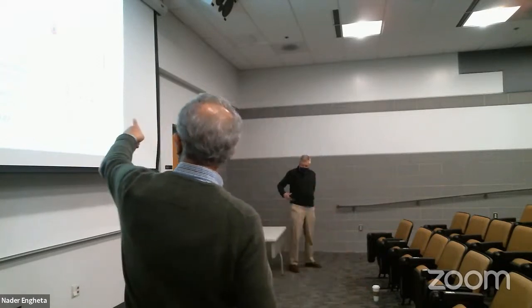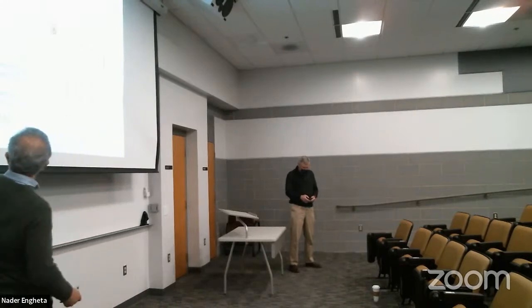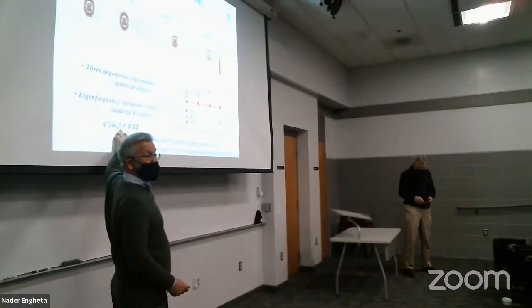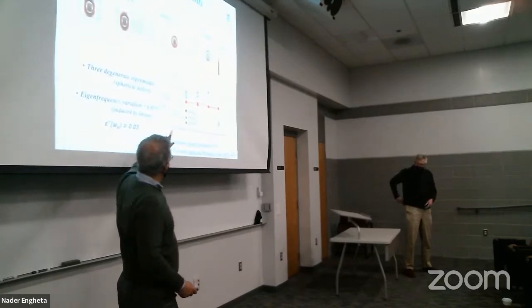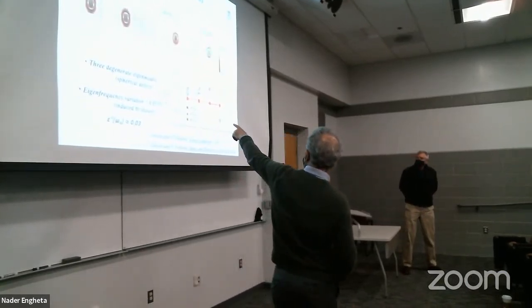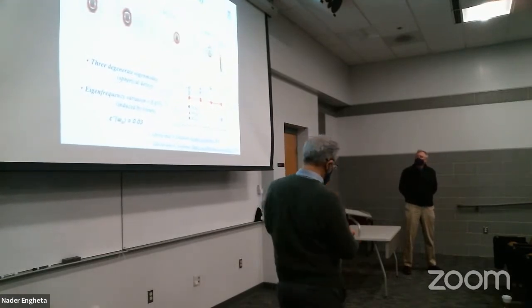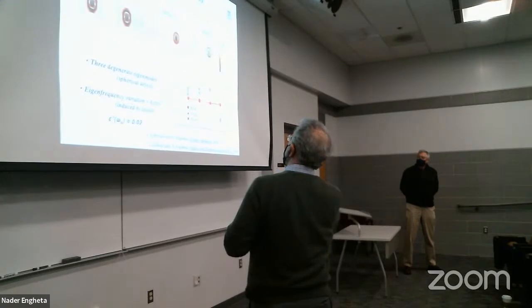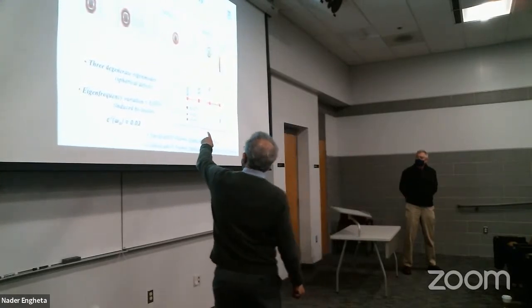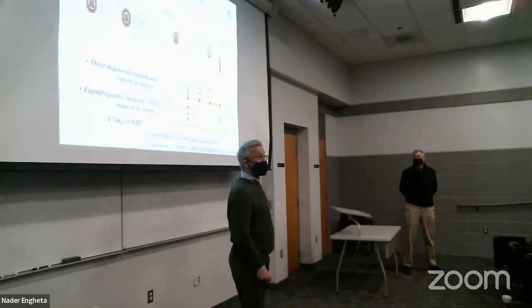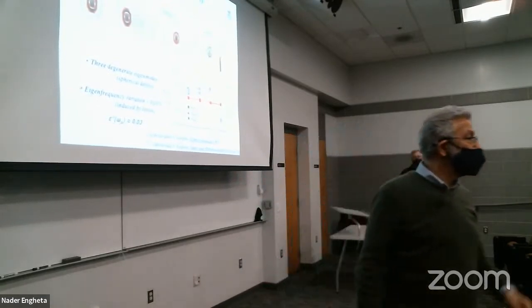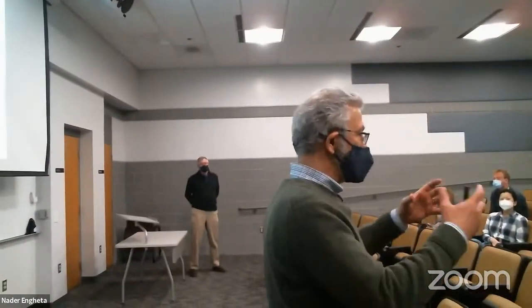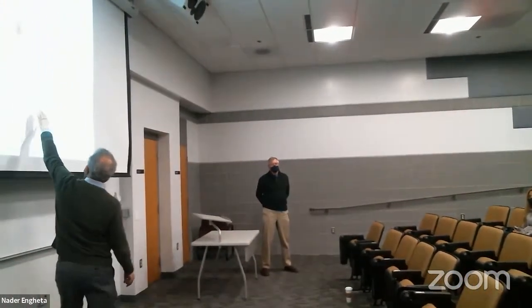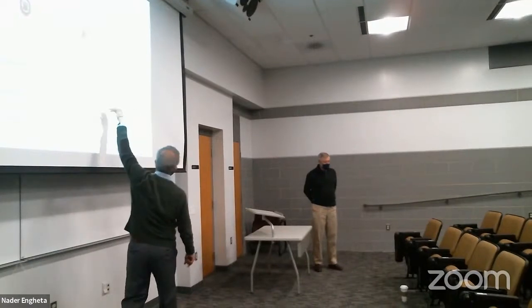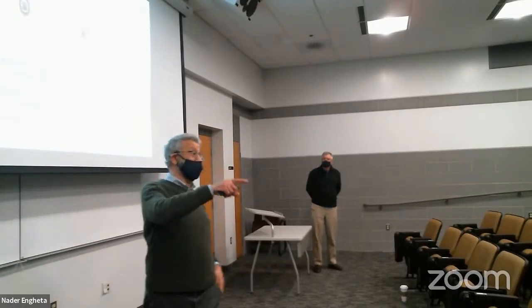In this one, we actually use the realistic material of silicon carbide with an epsilon double prime of 0.03. With this structure, you notice that the resonant frequency is almost unchanged, by the way, for these four cavities that you see over here. But look at the blue dots, and you see the range of the Q that you have there. So yes, obviously the Q deteriorates. And this is actually interesting because even though the resonant frequency doesn't change, the Q can change. And that's what we also saw in our microwave experiments.